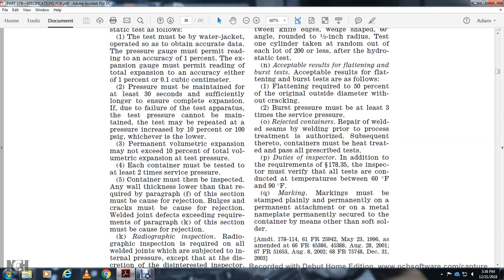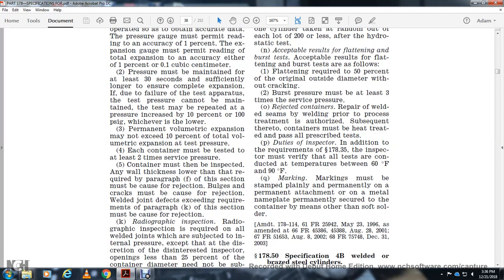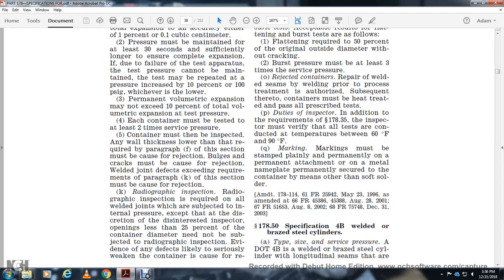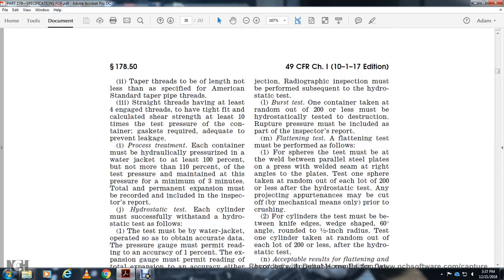Radiographic inspection. Radiographic inspection is required on all welded joints with internal pressure. Openings less than 25% of the container diameter need not be subject to radiographic inspection. Evidence of any defects likely to seriously weaken the container is cause for rejection. Radiographic inspection is performed subsequent to the hydrostatic test.